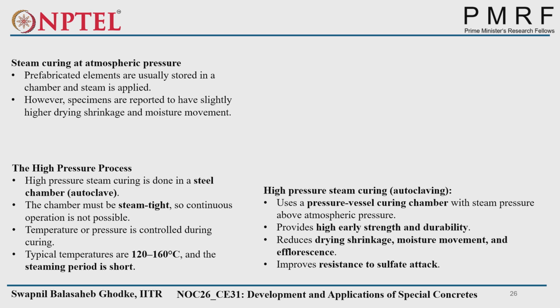You use a pressure vessel, a curing chamber with steam pressure above atmospheric pressure. As we are going above atmospheric pressure, high early strength and durability are obtained. Along with that, it reduces drying shrinkage, moisture movement, and efflorescence. So basically, two things are there. With atmospheric pressure, there is a possibility of higher drying shrinkage and higher moisture movement. But with the high pressure process, drying shrinkage and moisture movement are reduced. Along with that, there is resistance to sulfate attack also.